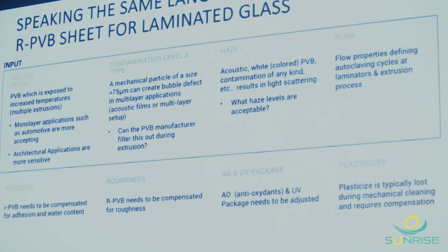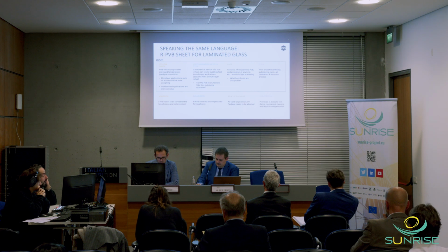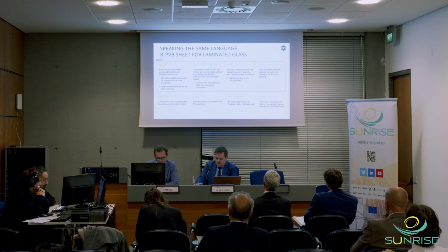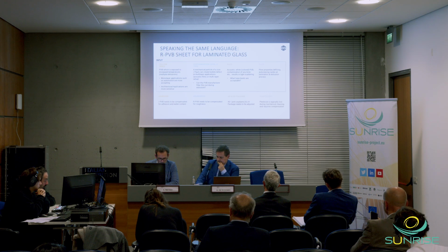I have put here, as an inspiration, a couple of very typical requirements from the PVB world, laminated glazing. Yellow index, very important. Understand what yellow index is, how we are increasing or decreasing it. Contamination levels, understand how many particles you are still allowing in your material. Anything above 75 micron, it's critical to mention it as a part of the quality of your material. The haze, very important. Understand how we are changing and controlling the haze, but of course also the physical properties like flow.